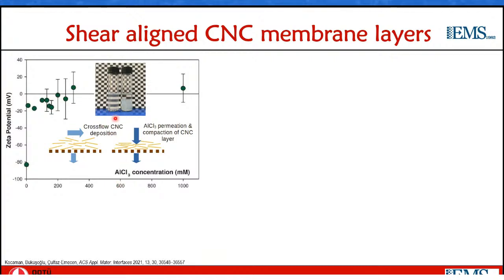So what you can see in the picture is what happens to the stable sol in this aluminum chloride concentration. And what we actually try doing is the same effect, but on the concentrated CNC layer on the membrane. Alternatively, this could also be tried by chemical cross-linking, which is also what we're currently working on.